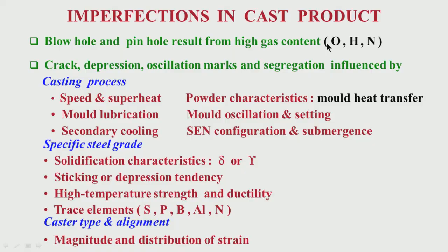The solubility of oxygen is quite high in liquid steel but much less in solid steel. So it will try to come out as gas. Therefore, oxygen, hydrogen, and nitrogen contained in liquid steel must be controlled before you do any casting, otherwise we will have blow holes and pin holes. This is one important type of defect.